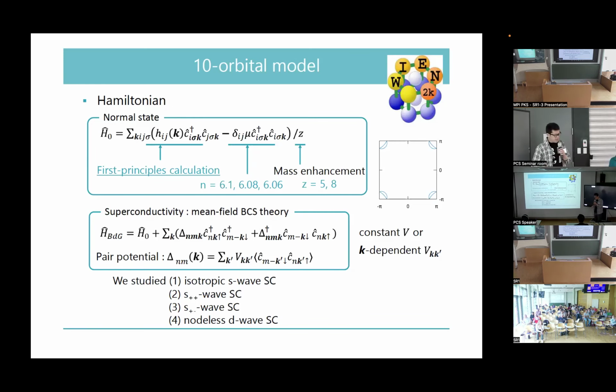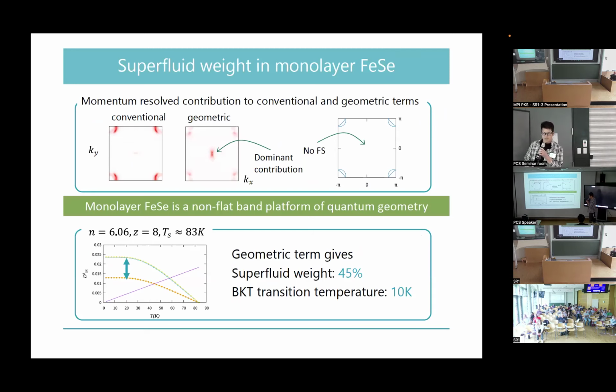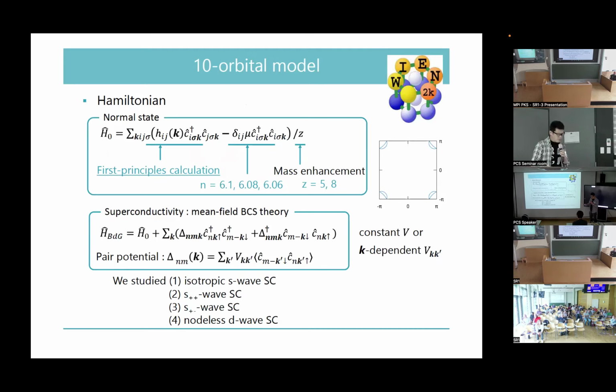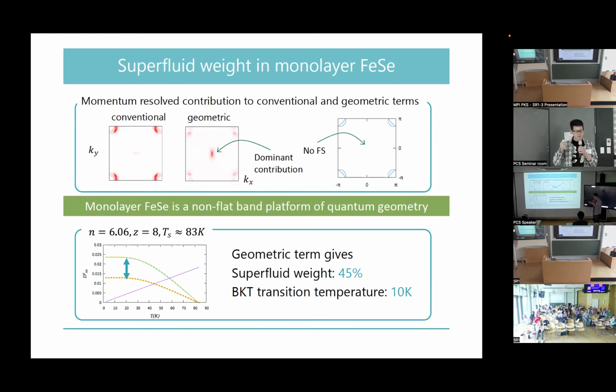So to evaluate the quantum geometric contribution to the superfluid weight in monolayer iron selenide, we carried out first principles band structure calculations and derived an effective model. And by solving this model using the mean-field BCS theory, we evaluated the superfluid weight. Here we have studied several superconducting states for this compound. Fortunately, we obtained qualitatively the same result for all the superconducting states. So therefore, I'd like to just show you the most simple case, the isotropic case of superconductivity.